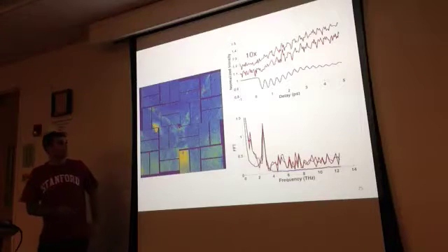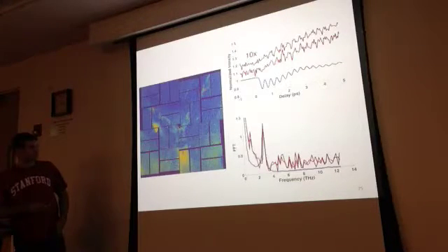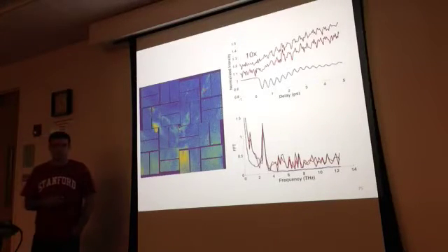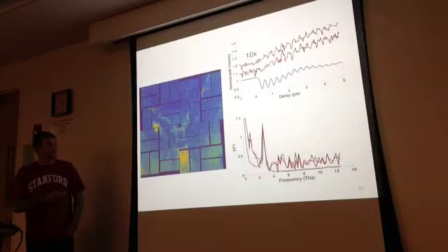So let me show you what the time-resolved X-ray intensity looks like in these regions. You can see that for this mode that we couple to directly, it responds very strongly right when we hit it with the laser pulse, right at time 0, and we get these big, beautiful oscillations that have been very well studied in bismuth. But these red curves right at time 0 aren't doing anything particularly spectacular. It looks more or less like it does before 0, when nothing was happening. But if we wait some time, we actually see that oscillations begin. And by checking the Fourier transform, we can see that in fact the frequency of oscillation of all these things matches up right at 2.8 terahertz.